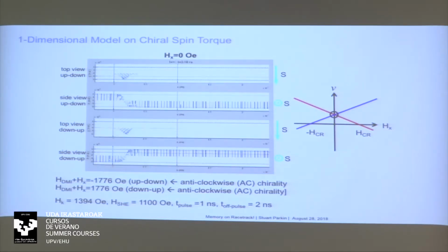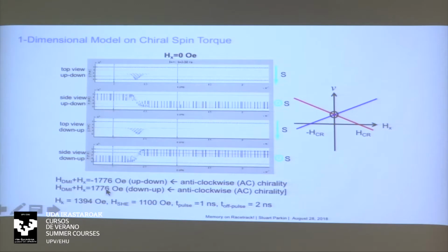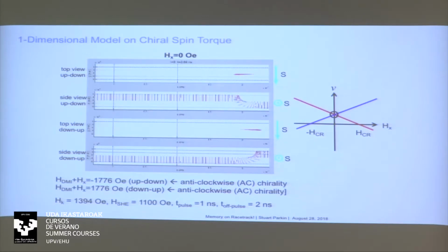And then if you look, this is how we model the nanosecond pulse. This is 1 nanosecond. You can see that this is what happens. The two domain walls move at exactly the same velocity. And if you look very carefully, you can see at the very beginning, the wall is rotating. The magnetization rotates to this sideways direction due to the spin-orbit torques.